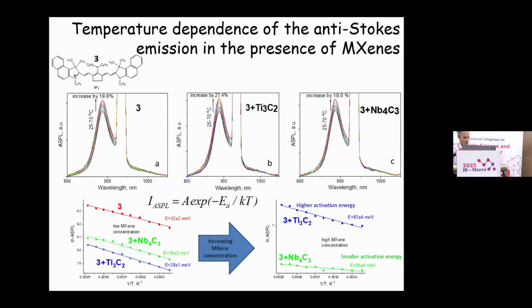And these studies showed that dependence on the temperature is different for the dyes in the solution without any nanoparticles, dye in the presence of titanium MXenes, and dye in the presence of niobium MXenes. You can see the different enhancement of the anti-Stokes emission for all these cases. And also we can calculate activation energy using this data, using this formula when we have integral emission here and temperature. And we can calculate activation energy, which is shown here, the numbers for activation energy for the different processes.